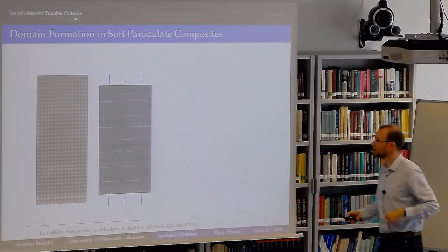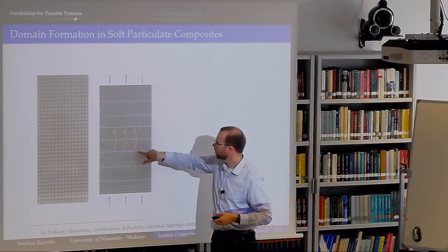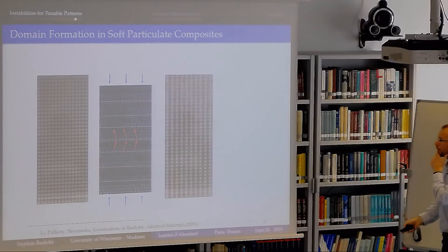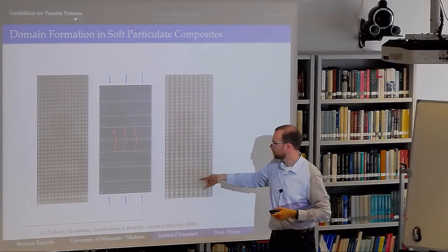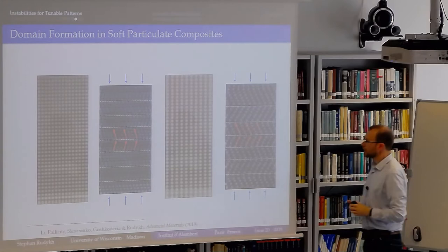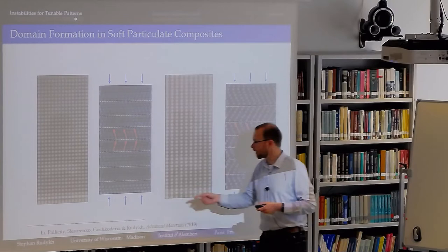If you look closely, and there is some cartoon to that too, you will see that there are some domains or some sort of twinning patterns that form, where one of these domains is aligned with a bunch of inclusions in one direction, and the other one is this anti-symmetric case. So it actually happens. We can change this behavior by changing the spacing, this simple geometry here, and still get this very nice structure. The instability here is predicted by these. And actually, if you use Bloch-Floquet analysis here with the effective moduli and homogenization, you do predict quite accurately when it happens.